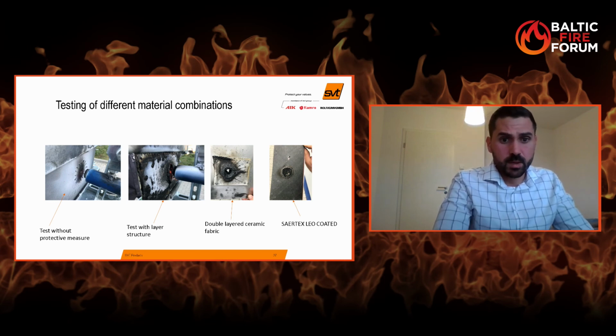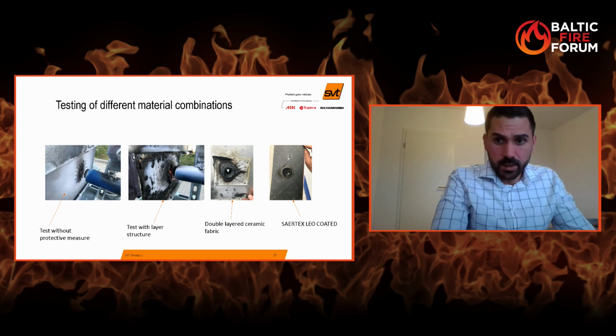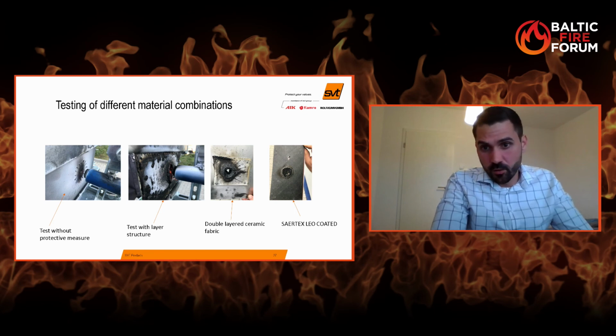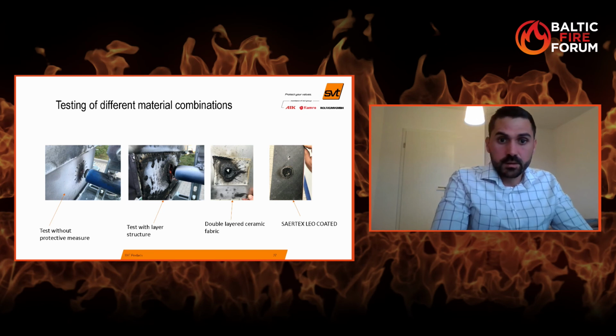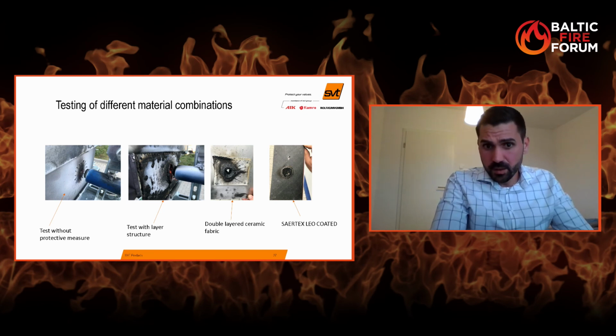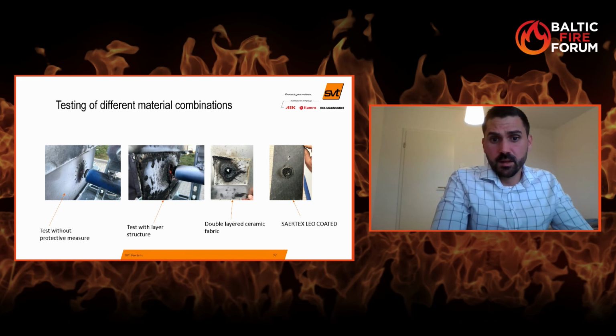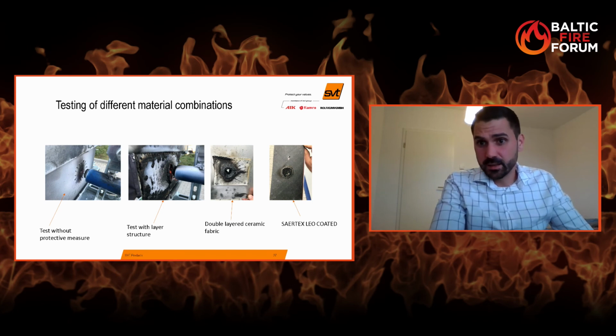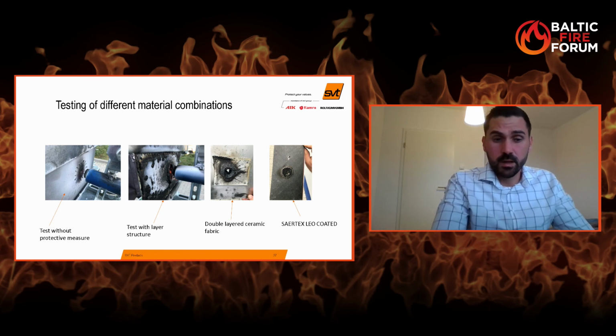We have tested this with some layer structures of our fabrics and our coatings. We got the double layer ceramic fabric, as you can see the hole in the middle of the substrate, that protects the aluminum plate for about 6 or 7 seconds, and it's double layered ceramic. So as you can see, there is a lot of temperature, a lot of erosion. That's the really strong impact that the material has to withstand.